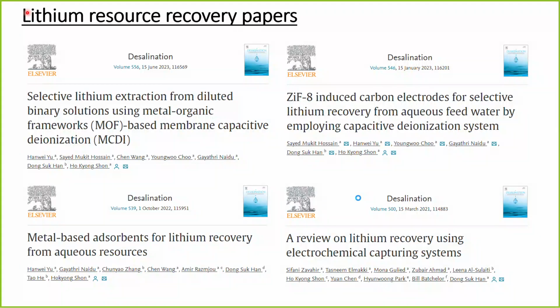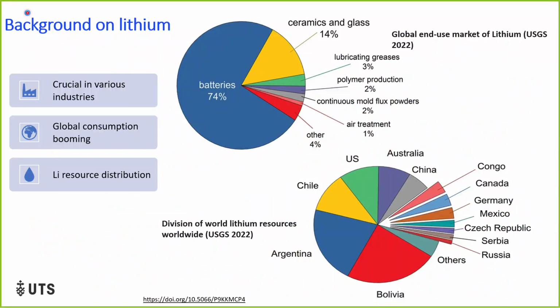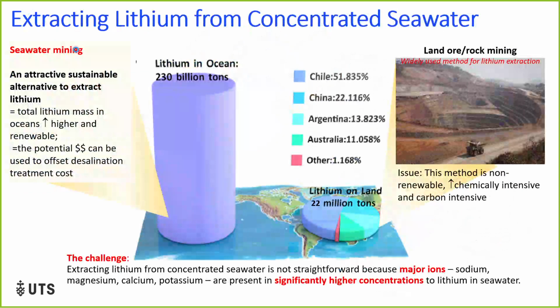We have also worked in this area for the last 5 years to recover lithium from seawater. I want to skip the general background of lithium and inland lithium exploration. Chile, Argentina, and other countries have a lot of lithium on land, but it is only 22 million tons. However, in seawater, the lithium concentration is almost 0.2 milligrams per liter, which is 230 billion tons, which means almost 10,000 times more lithium is contained in seawater.